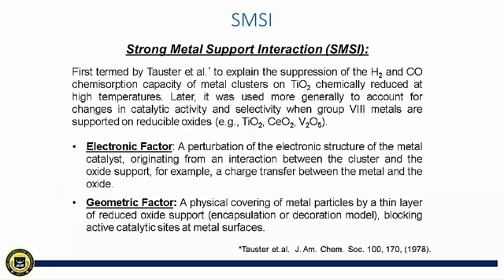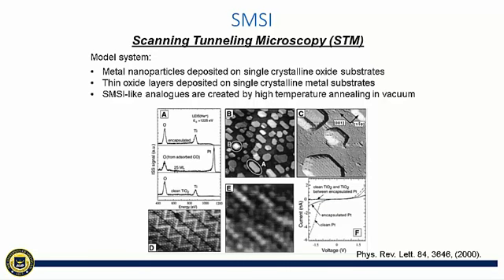The term SMSI was first used by Sam Tauster and his colleagues at Exxon Research Labs to describe the suppression of hydrogen and carbon monoxide chemisorption by metals supported on titania following reduction at high temperature. Many such examples involving reducible oxide supports were identified and studied extensively over the years. Both electronic and geometric factors were considered as possible explanations for the effect, but eventually it became clear that a thin layer of partially reduced oxide was migrating onto the metal particles, blocking access to gas.